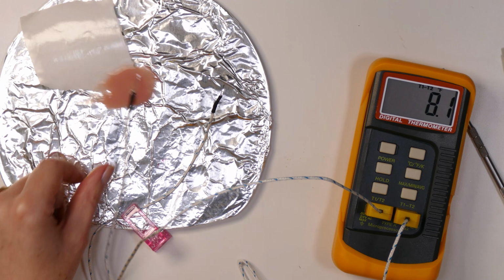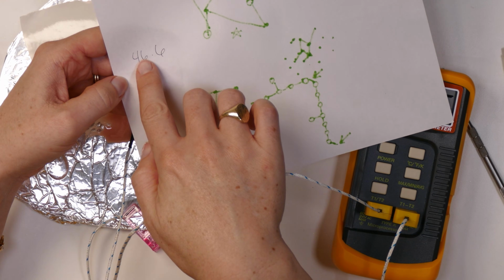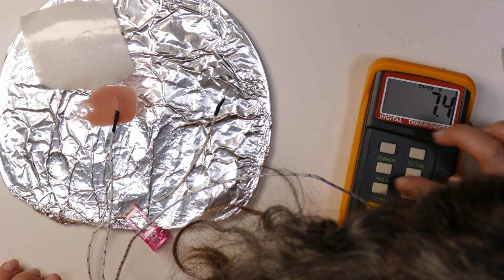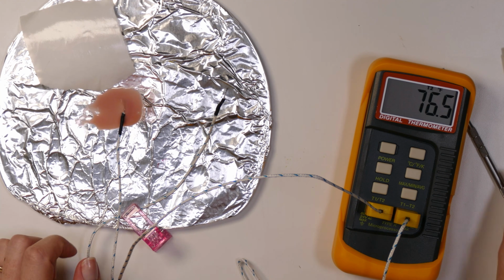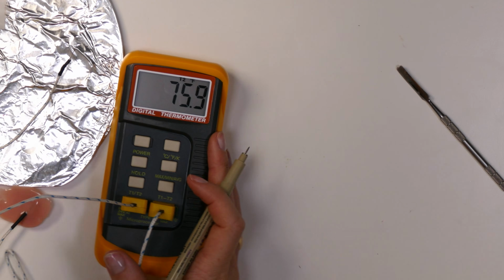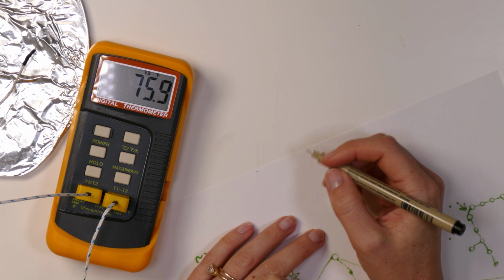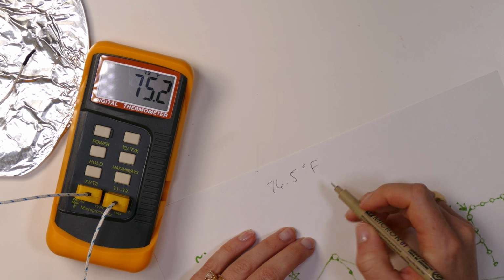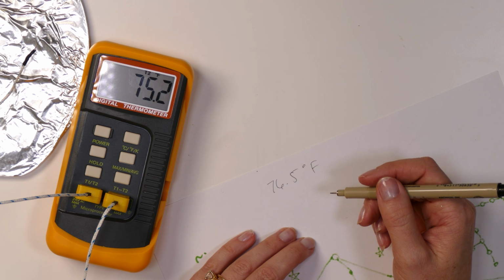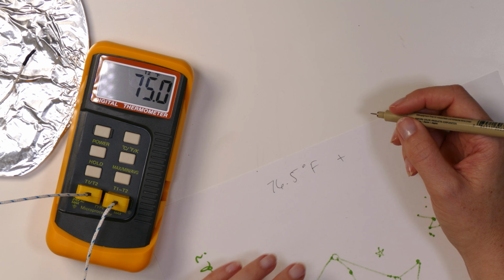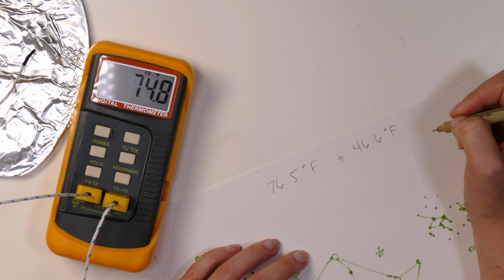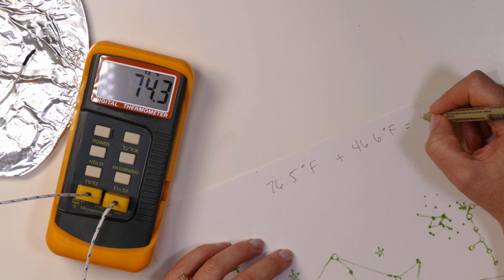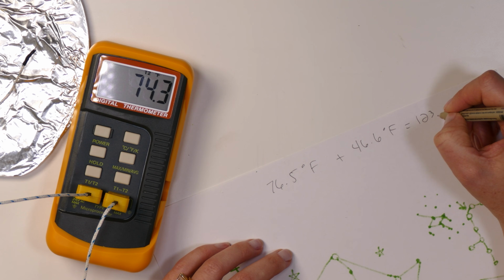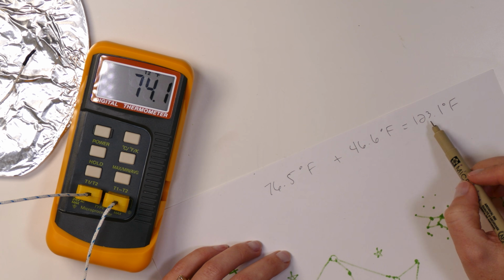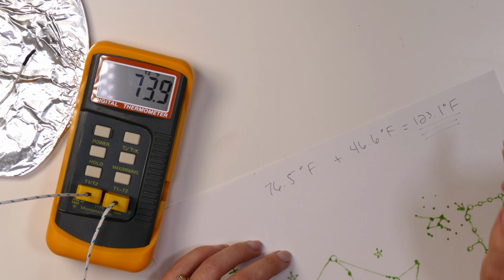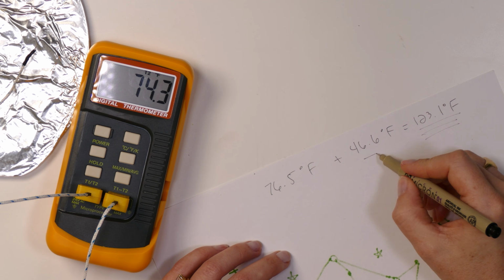So what this tells us is that on the first round of curing, okay, I wrote down my number here, 46.6. So my ambient temperature right now, let me just get you my ambient temperature. Okay, so my ambient temperature right now is 76.5 degrees. So we have 76.5 degrees Fahrenheit is basically the temperature of just the air that was around the gel, okay? And the gel was hotter than that by 46.6 degrees Fahrenheit. So that means that the max temperature that this gel basically would feel like is 123.1 degrees Fahrenheit. Okay, so this is the heat that would have been on the nail at the time that the gel fully peaked for its exothermic reaction, because this was the hottest that it ever got inside the lamp.